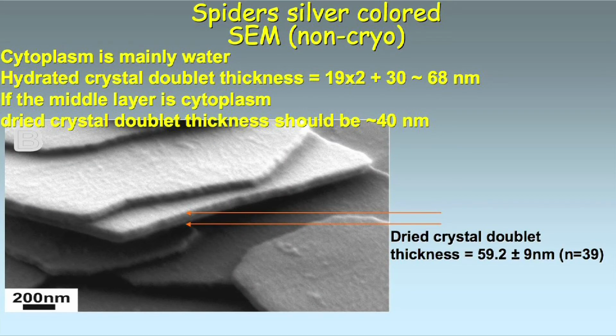And in order to show that, in fact, it was quite easy. We dried the crystals, and when we dry the crystals, the thickness of the crystal goes down. But it doesn't go down as much as we would have expected if this was a layer of cytoplasm that's practically water. So it went down only a few nanometers, much less than what we would have expected if it was water or cytoplasm. So we conclude that in fact, the layer between the crystal doublets is amorphous guanine.